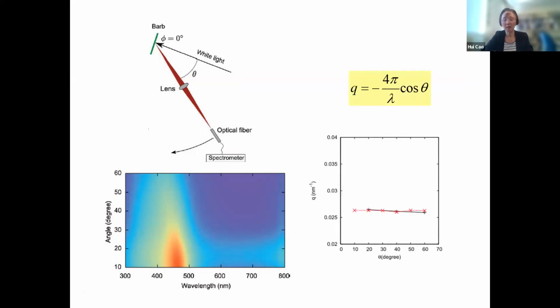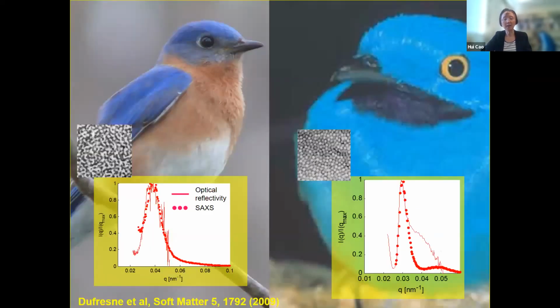So from the peak position of this reflection, and also from the angle, we can recover the spatial frequency of the structure. And we find it is the same in all angles. That means this structure is isotropic, but has some dominant spatial frequency that determines the color of the reflected light. So that is what we learned. Then we tried to confirm this by placing the optical reflection spectrum on top of the X-ray scattering peak. Then we see they really match pretty well here.